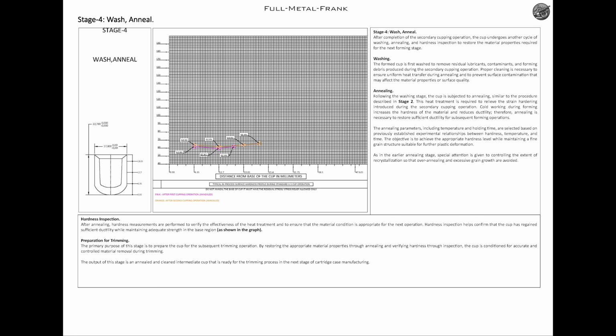Annealing. Following the washing stage, the cup is subjected to annealing, similar to the procedure described in Stage 2. This heat treatment is required to relieve the strain hardening introduced during the secondary cupping operation. Cold working during forming increases the hardness of the material and reduces ductility. Therefore, annealing is necessary to restore sufficient ductility for subsequent forming operations.